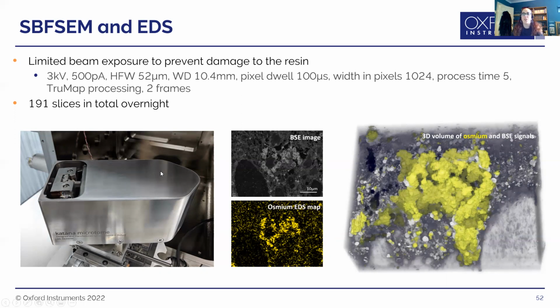What we wanted to do was see if we could use this with the Ultim Extreme detector. It would not be possible to use this system with a normal EDS detector because you wouldn't have the right working distance between your sample and the pole piece, and you have the potential for the X-ray signal to be shielded because of the knife position. But with the Ultim Extreme detector, because we can get so close to the sample, we can still get a decent signal even at those lower kVs.